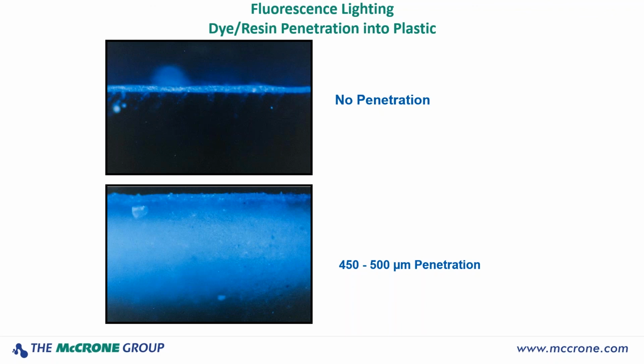And that forms during the molding operation. So the cure for that was to change the parameters in the molding operations to minimize and eliminate the formation of the polycrystalline polypropylene at the surface. So the dye, the chromophore dye, was added to the resin in the part.